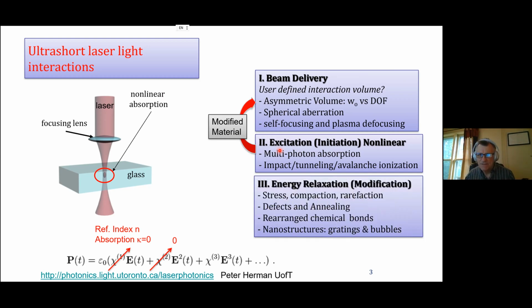What happens to the material, of course, happens during and mostly after the laser as the material cools. There's stress, there's compaction, which might give refractive index changes, or rarefaction. There could be bubbles forming. There could be a more gentle forming of chemical bonds, rearrangement that leads to defects, or you could turn on annealing effects. There's also nanogratings forming in the fused silica glasses, which is what we're mostly focusing on. And so the net result is, instead of damage, in here is really the possibility of controlling processes, modifications. And so I like to call this seeking the magic in Chi3.